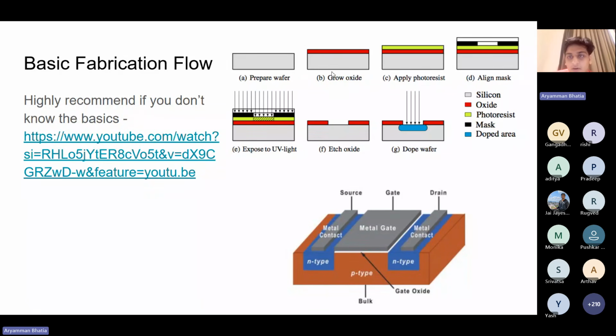you grow an oxide layer on the wafer. You apply a photosensitive compound called photoresist, and then wherever you want the windows to be, you expose UV light through a mask to those windows, and that UV light changes the solubility of the photoresist, and it can be washed away in those parts. Then in the parts where the photoresist gets washed away, you can dip the wafer in something like hydrofluoric acid, or you can do a plasma etch, and you can etch the oxide away. So that will expose the bare silicon. And when the bare silicon gets exposed, you can dope that part. So that's how you dope these N-type windows. And then once you're done with doping the N-type windows and growing the oxide, you figure out a way to deposit the metal, and that's how you build your transistor.